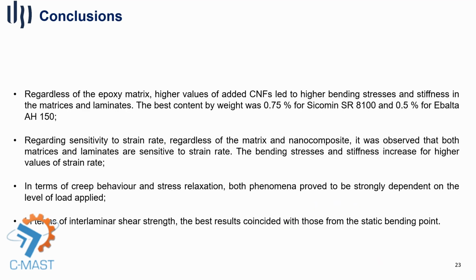Main conclusions. Regardless of the epoxy matrix, higher values of added carbon nanofibers led to higher bending stresses and stiffness in the matrix and laminates. The best content by weight was 0.75% for Sicomin SR 8100 and 0.5% for Ebalta.